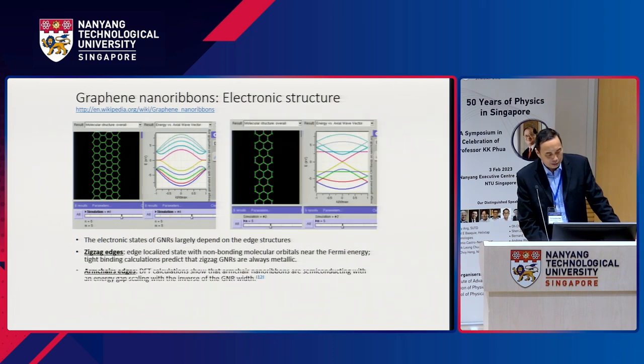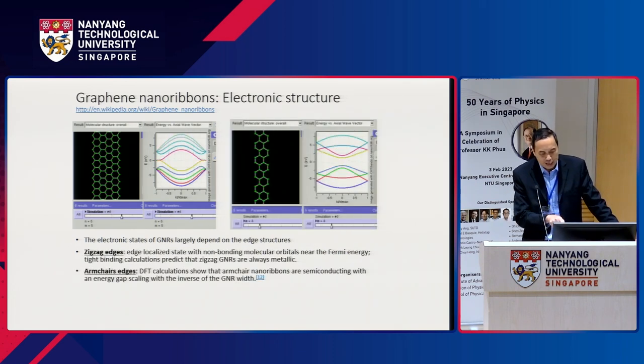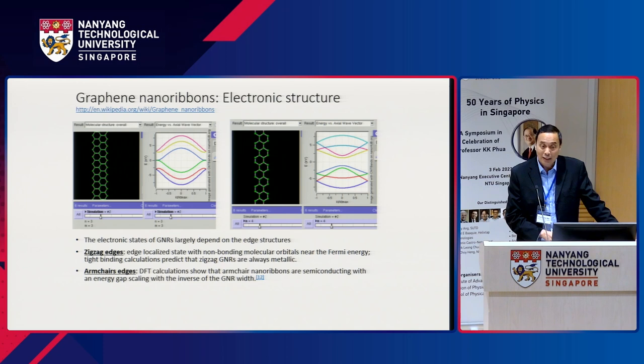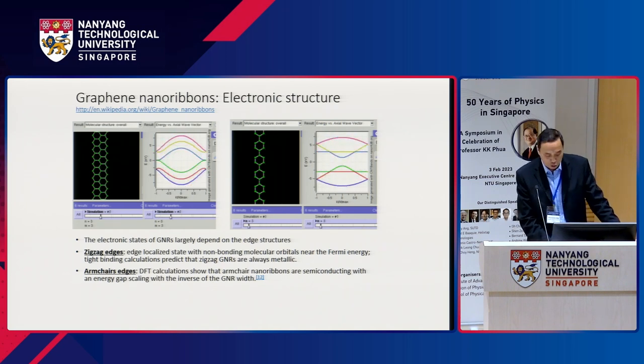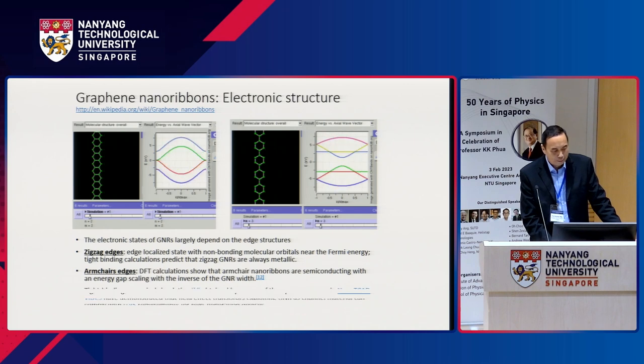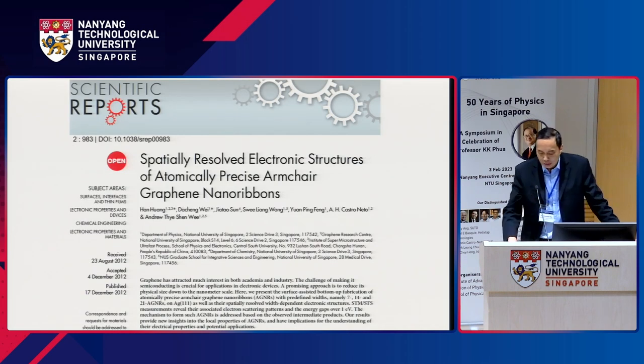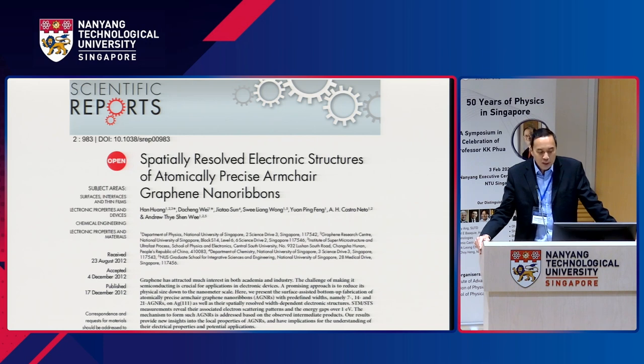Whereas on the armchair edges, it's semiconducting except for certain widths. Okay, it's semiconducting, so you want to make armchair semiconductor ribbons. That's an additional challenge you have in graphene nanoribbons. While many people make graphene nanoribbons in the top-down way, for example using e-beam lithography or some other way of cutting, we know that's quite difficult because, first of all, they are very small. And secondly, after you cut them, how do you control them and move them about on your device?